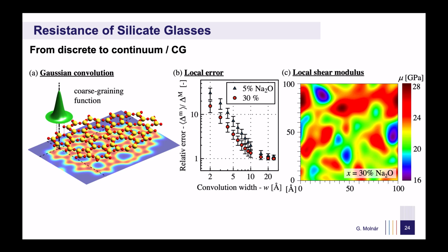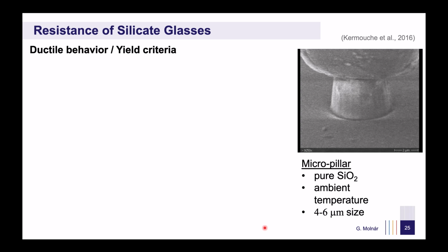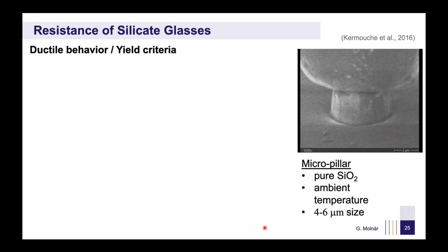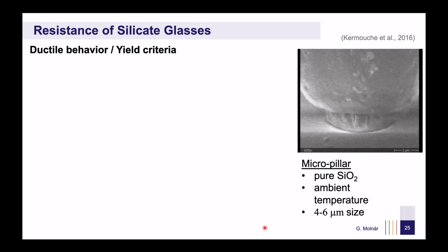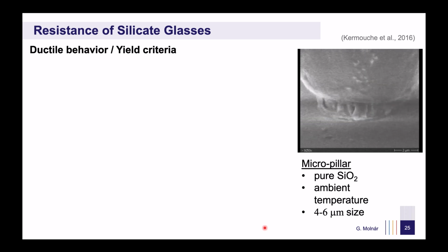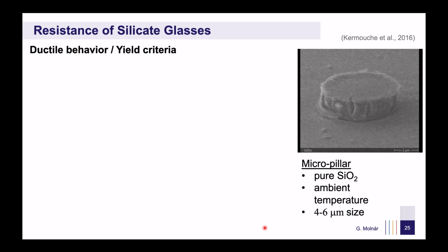Through this approach, we identify the first length scale, the minimum region in which a discrete material can be considered a continuum. For silicate glasses, this length scale was found to be around 8 to 10 angstroms. Although glasses are brittle at the macroscopic scale, they can exhibit plastic deformation if the sample is small enough. For example, here we see a micropillar made of pure silicon dioxide deformed at room temperature. We can see that the micrometer scale glass can behave like Play-Doh.